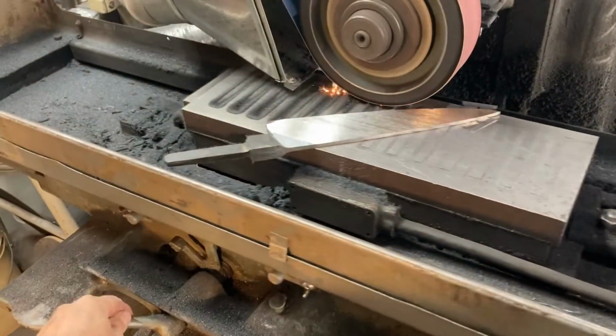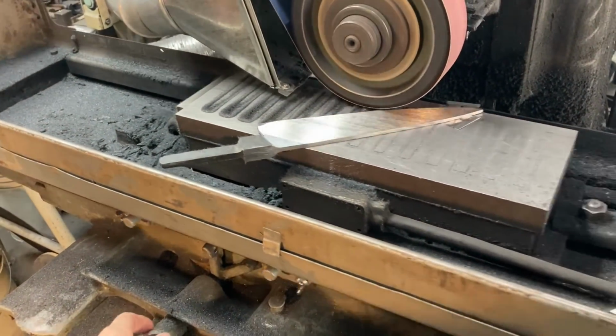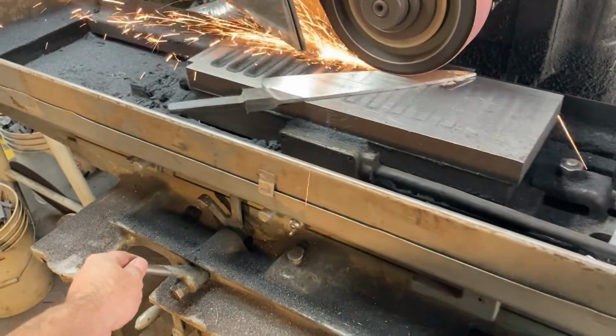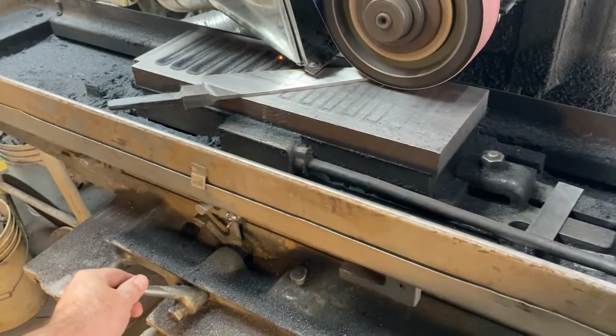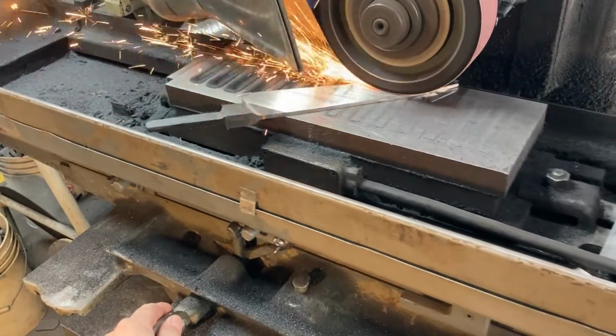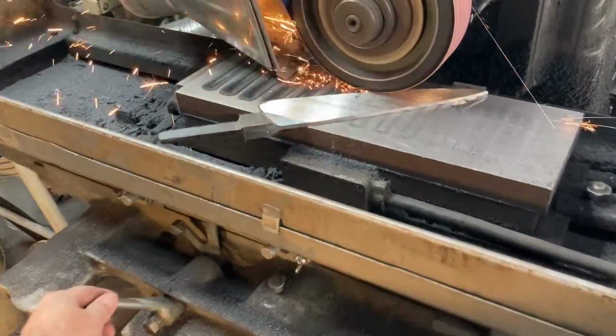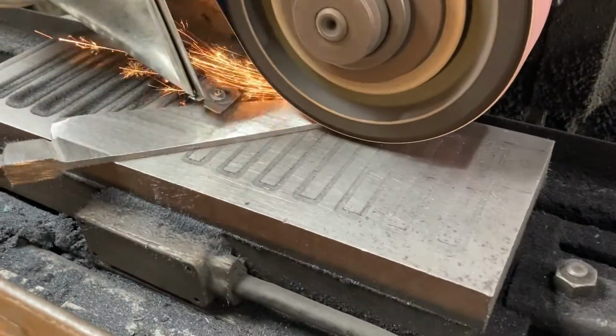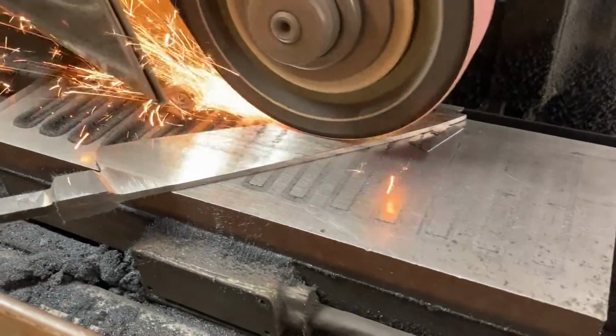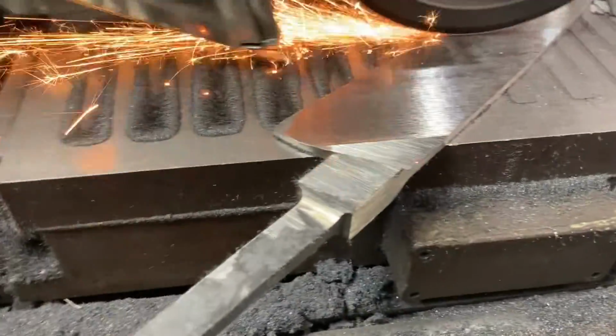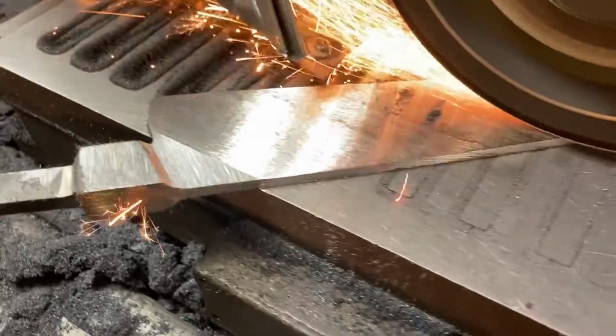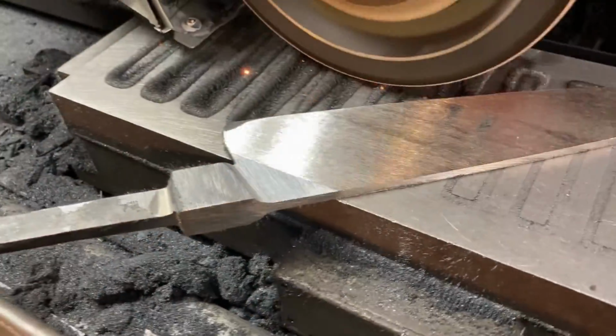Here's how I hold them on the surface grinder at an angle on the chuck with the bolster hanging off. And I'm just taking the thickness down to about 120 thou flat all over before heat treat. There's a little wedge of blade unground right in front of the bolster. You can see there a triangle wedge. And every time I flip the knife, I just freehand grind that little bit of material the surface grinder can't get to.